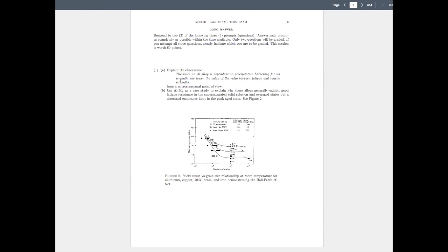You get softening and have a natural persistent shear band, which is going to kill your fatigue life. You'll just constantly keep ratcheting back and forth on that same slip plane, and every time you do it, you're going to make your particles smaller and smaller until you dissolve them away. Then you have no strengthening there.